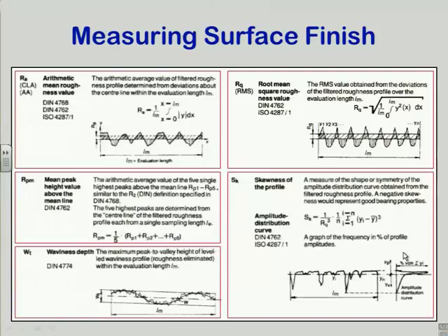So the character of the surface is such that it is somewhat truncated in a positive direction and not in a negative direction. And its positive skewness is exactly the reverse. So it has more mountains than valleys. In general, grinding will give me a negative skewness because the grinding process is knocking off the mountaintops and leaving the valleys. Whereas a milling process will give me a positive skewness because, like taffy, it's pulling these up as it tears the metal apart, if the metal is ductile.